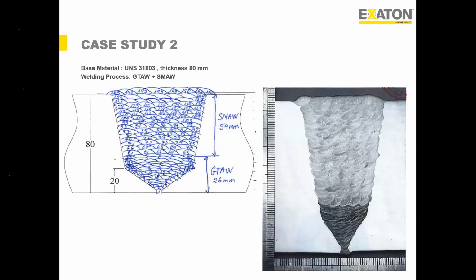Then we found the welder can't go to the root side because of the high thickness. The torch will not go, and the torch angle is not suitable. So it will form a very high arc length and a very high potential that it will not melt the weld metal. So we decided to do 20 millimeter with the TIG. After we did the 20 millimeter TIG, we found that we now had enough access with our electrode. But when we tried to start welding with the electrode, especially because of the impact requirement, we have to use the LB or basic type electrode, where slag detachment is very challenging.